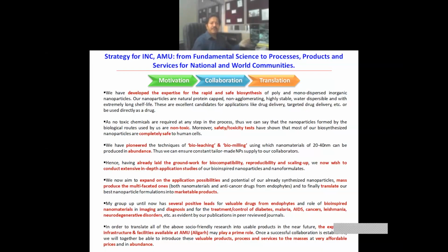They are highly fluorescent in nature, very important for diagnostics and solar cells. And then I made CdTe nanoparticle. Again, I did a very simple reaction. I took cadmium chloride and tellurium chloride, reacted with the fungus, and the fungus converted the cadmium chloride and tellurium chloride into CdTe nanoparticle.